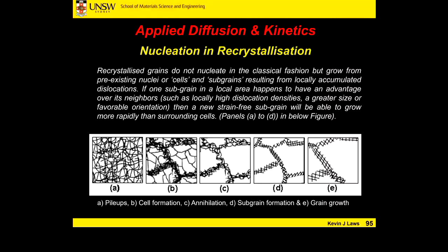In certain cases, they will be localized because of this tangling process, and this localization of dislocations starts to form a cell. This cell of material starts to behave independently of the parent grain. Sometimes the atoms within that cell can start to rearrange themselves or rotate during deformation.